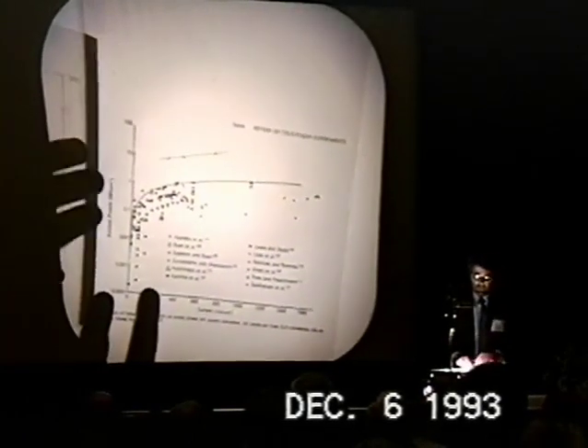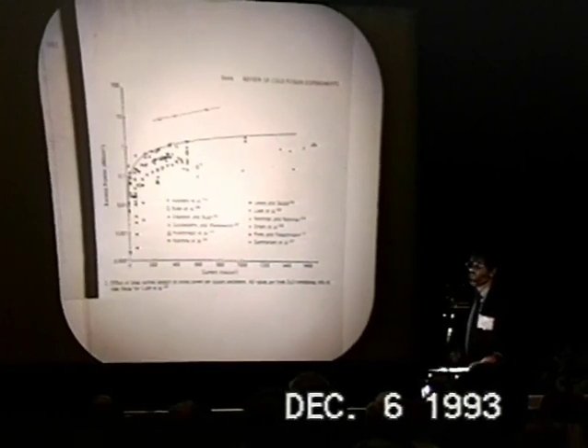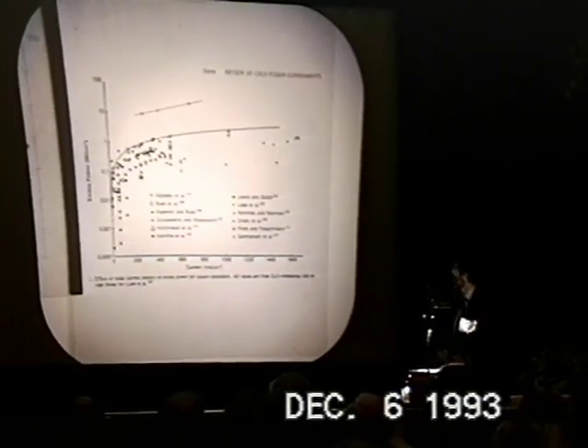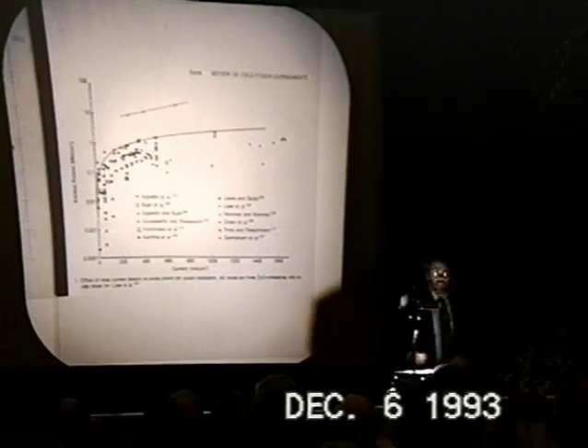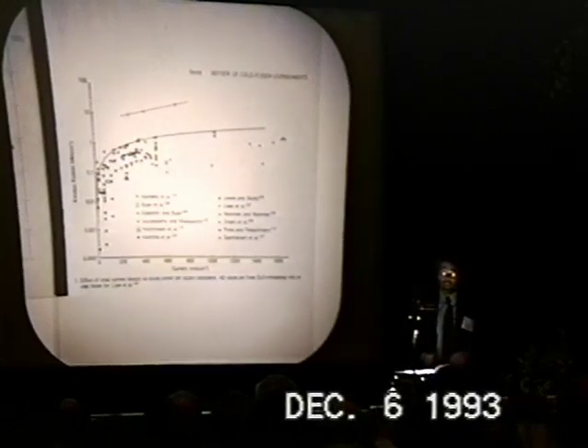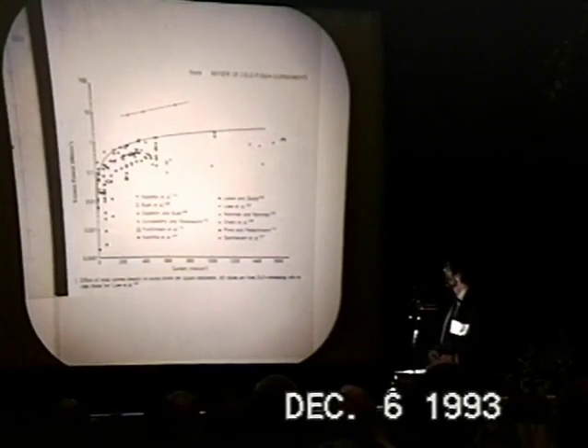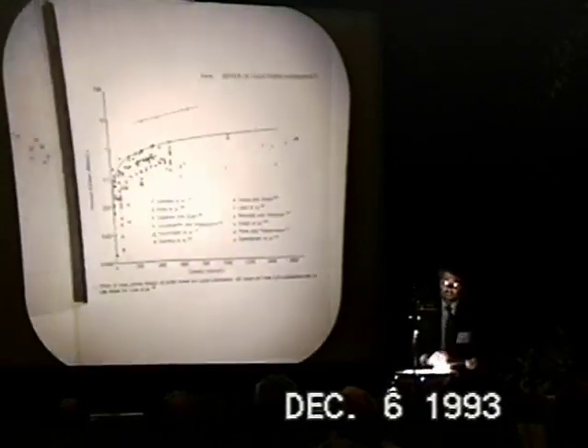If the cold fusion trigger, as we believe, is a high D/Pd ratio, the deuterium confinement results indicate a route to reach heat. And finally, let me present a piece of pathological science. In 1991, Edwin Storms published a review on fusion technology, and they reported the thermodynamic data known at that point on the scale of excess power per square centimeter with respect to the current density.